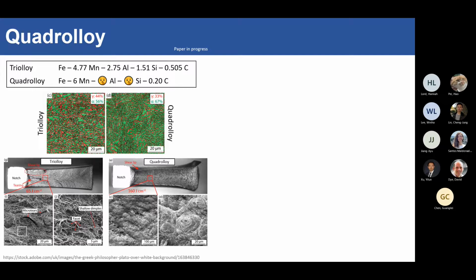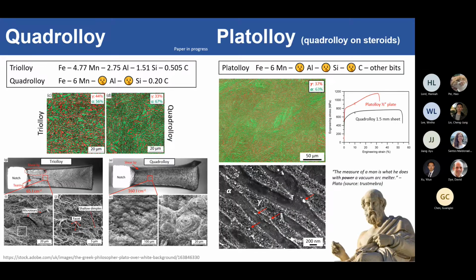And around this time, we also had some interest from industry about medium manganese plate. So everything I've been talking about so far was medium manganese sheet. Sheet is between 1 to 3 millimeter thickness. Plate is about half an inch to 1 inch. So we've gone again to develop a plate alloy, and therefore we've come up with Platolloy.